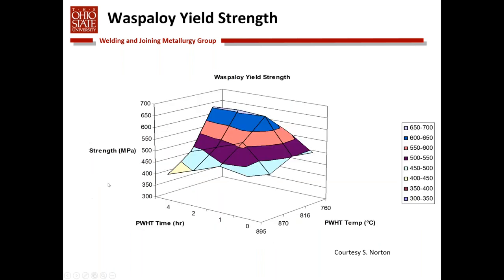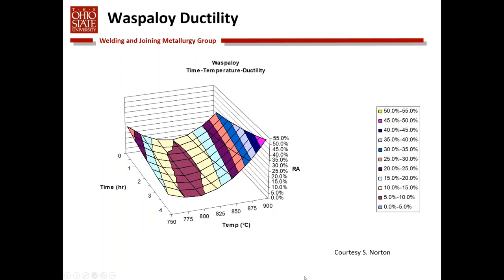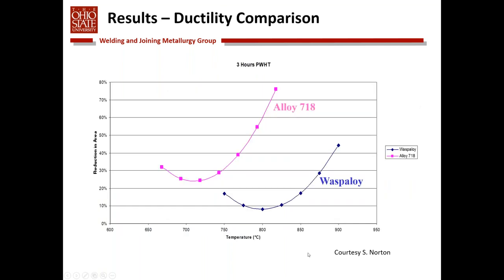So based on this test, we can develop three-dimensional plots of strength, post-weld heat treatment time, and post-weld heat treatment temperature, that depicts both the yield strength, but probably more importantly, the ductility of the material, and basically indicates a ductility trough. We can take different times and temperatures and put them into a plot. So here's temperature after 3 hours of post-weld heat treatment.